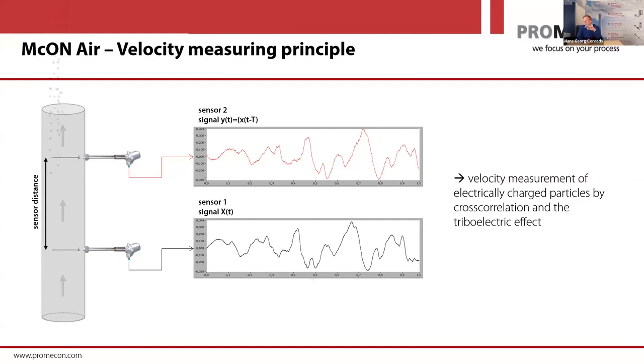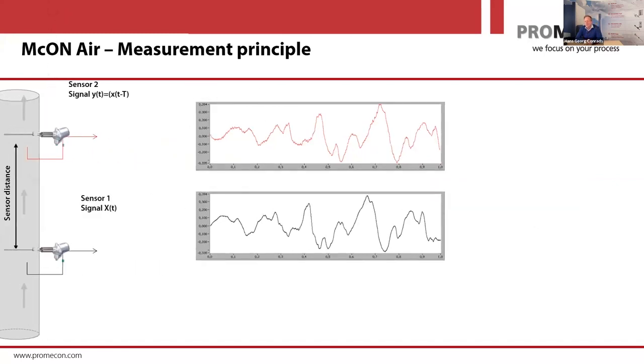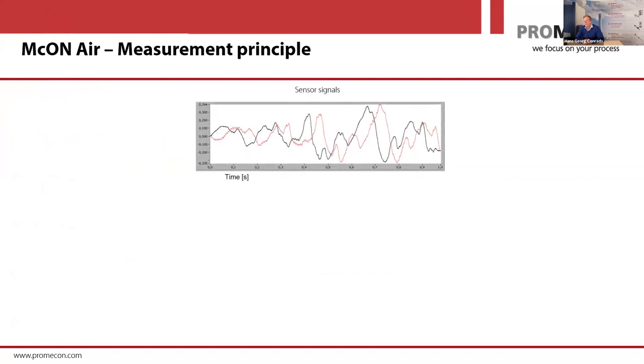If you do that on an upstream and a downstream sensor that are spaced very closely, like 300 millimeters, you can see that this pattern is very similar. You can see with your own eyes, the upstream and the downstream patterns look pretty much the same. And this is because the flow dynamics from one sensor to the other do not change instantaneously. It takes some time for them to change. So if you are within a certain short distance, you can see that this information is more or less kept the same. The only thing you can see is that it's time shifted because you're not at the same location. And this way it becomes digital.